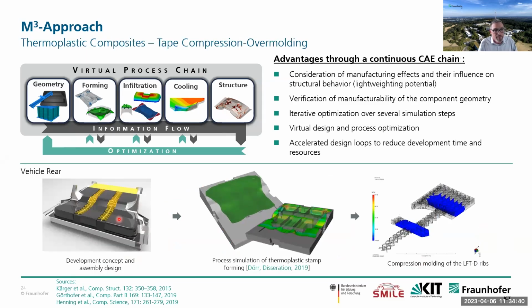Now the back structure you see here is a tape placement, or organosheet if you like, thermoplastic, hot, then molded, as you can see here, with a segmented mold. So it's like ironing a textile from the top to the bottom, from the inside to the outside, in order to avoid wrinkles. That has been determined. So by the simulation, we can predict which area has to be draped first and which last, in order to avoid wrinkling and get an appropriate